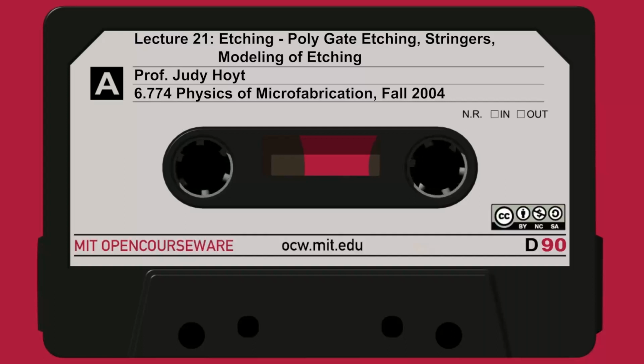How deep will we have to etch? Reasonably deep, somewhere between 5 to 7 microns is what people are talking about doing. Aspect ratio. So remember, we talked about aspect ratio as being an important attribute of our capabilities for etching. Well, here's the trench depth divided by its width. We're talking about very high aspect ratios that are increasing, and they're also quite large.